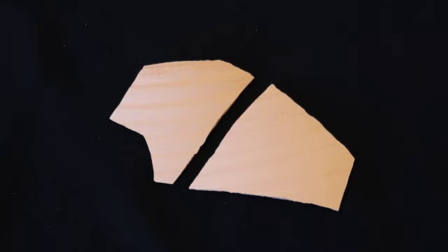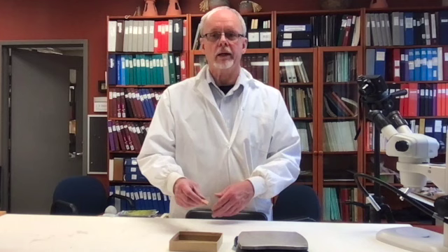After a relatively low temperature refiring of the sherd on the left we see no difference in the color of the sherd so we now refire it yet again at a somewhat higher temperature, let it cool off, make a comparison with its partner sherd and repeat this process at slightly higher temperatures, perhaps in 50 degree Celsius increments or something like that,